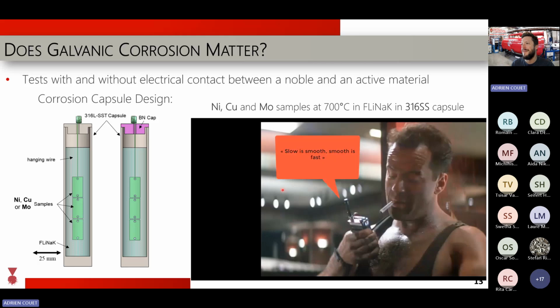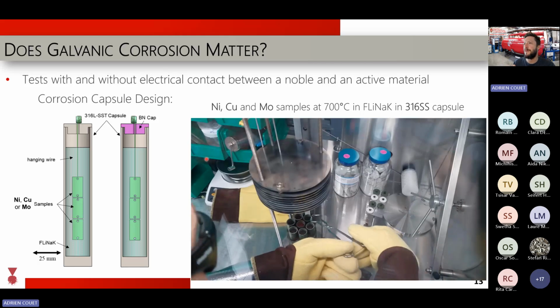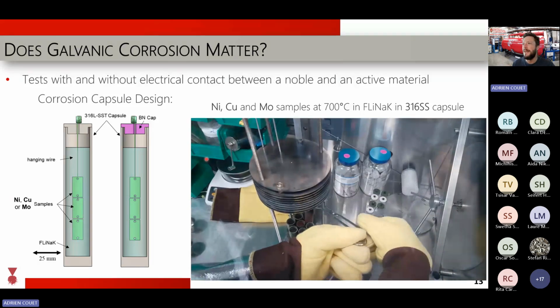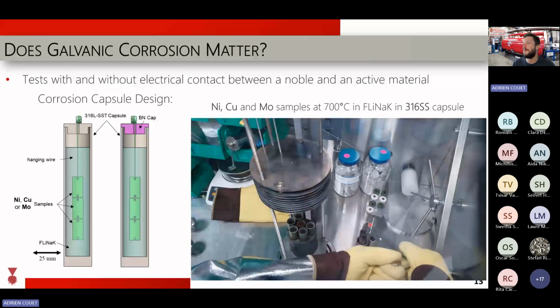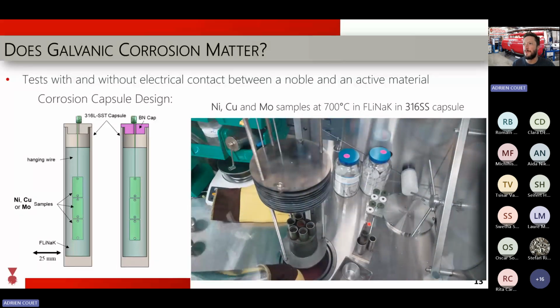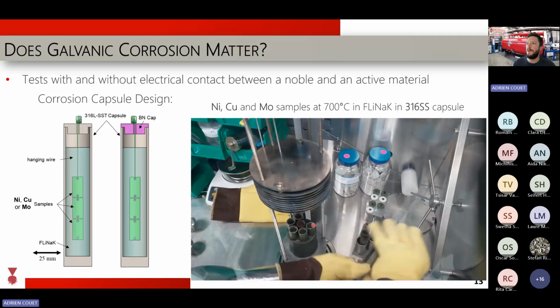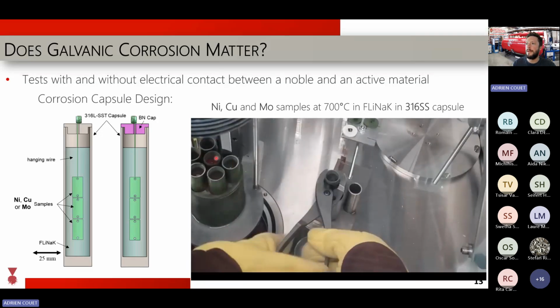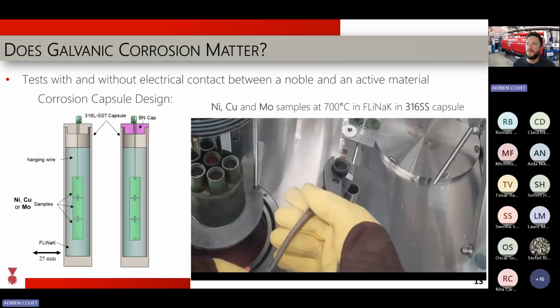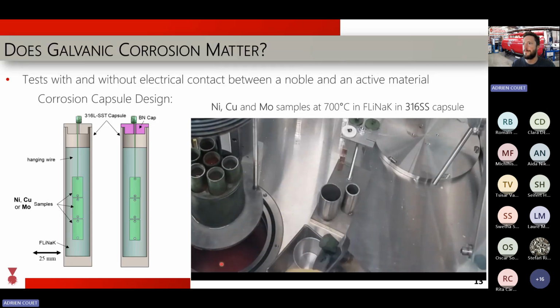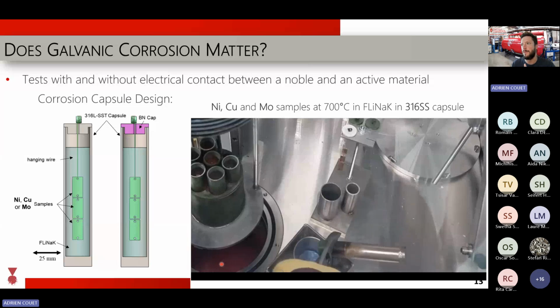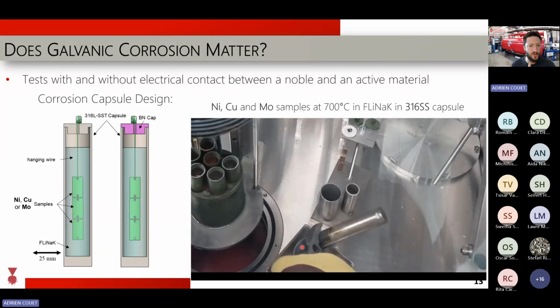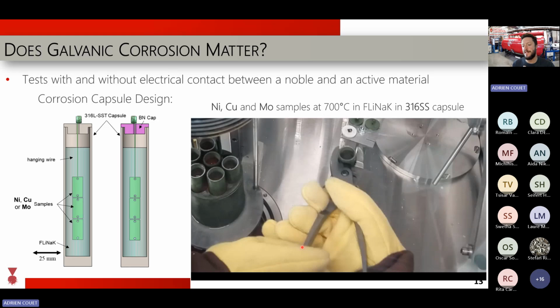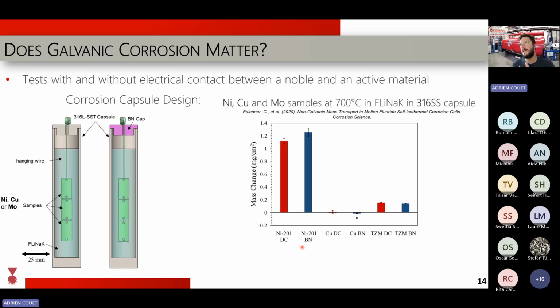I forgot to remove that one from Bruce Willis, but anyway, it's very hot in there, so you've got to know what you're doing, and that's about 700 degrees Celsius. You've got to work with it here, and the salt is still liquid, and we are retrieving the salt to get the chemistry of the salt using ICP-MS afterwards. You see the salt a little blue here. There are corrosion products in it, and so on. So this is typically the type of test we do, and then we weigh the sample. We clean it up, and then we weigh to see how much material it has lost.